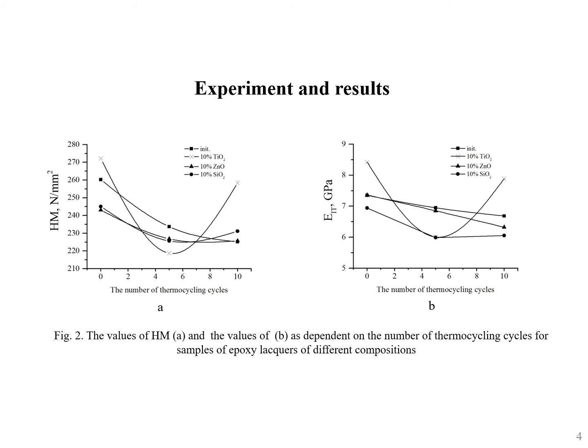Thermocycling has the most noticeable effect on the coating containing titanium dioxide. Initially, this coating is the hardest, with its hardness value falling from 270 N per square millimeter to 220 N per square millimeter, i.e. by 20% after 5 cycles of thermocycling. After 10 cycles, the value of hardness increases to 260 N per square millimeter, thus exceeding the hardness values of the other samples, but being lower than the initial hardness value. A similar situation is observed for modulus, i.e.